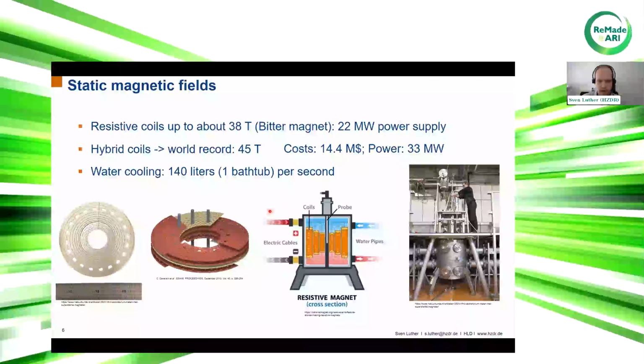And if you want to go above these 22 Tesla, we have to use resistive coils, so-called bitter magnets, and they can create magnetic fields up to 38 Tesla. But they need lots of power, up to 22 megawatts of power supply. If you combine such a bitter magnet with a superconducting magnet, you can create a hybrid coil, and here the world record lies at 45 Tesla of highest magnetic field generated. But this one has an extremely high cost, about $14.4 million, and also needs lots of power, 33 megawatts.